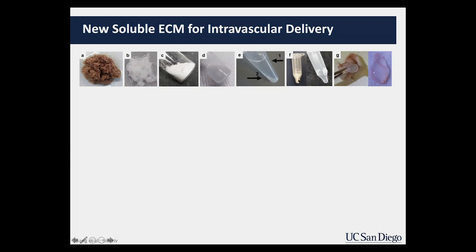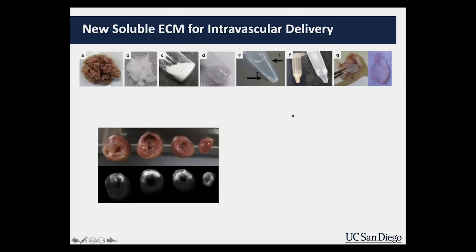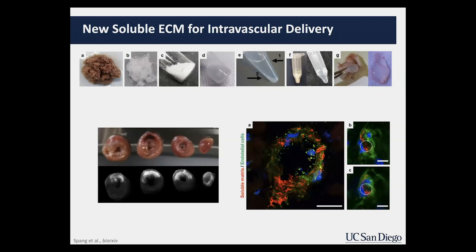The soluble component can be re-dried and rehydrated with sterile water prior to injection. If injected under the skin it will form a gel, but when delivered intravascularly — injected into the bloodstream — it targets and gels at areas of inflamed tissue. Here's an example of a rat heart given a heart attack: our fluorescently labeled material is actually retained at the infarct, the region of heart attack, and under a microscope you can see the material gels and fills in the gap.